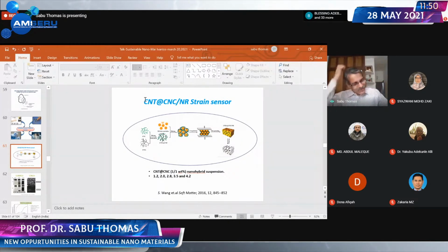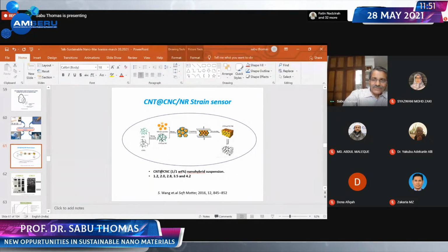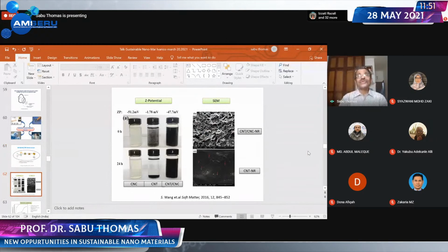If you want to make a sensor, we need to have a conducting material because it works on the principles of conductivity. So if you look at this manufacturing process, nanocellulose crystals and CNT, mix them together, and then you mix with natural rubber latex. Go for a coagulation process. And then you go for pressing, and finally you get a natural rubber composite filled with nanocellulose and CNT. In the next slide, you will see the purpose of combining nanocellulose and CNT together. You will understand the reason.